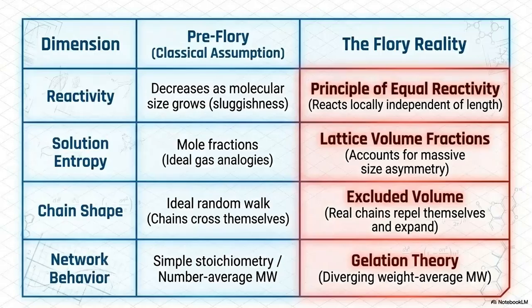For solution entropy, he replaced inadequate ideal gas analogies with lattice volume fractions, which account for massive size asymmetries. Regarding chain shape, he updated the ideal random walk assumption to incorporate excluded volume, recognizing that real chains repel themselves and expand. Finally, for network behavior, Flory replaced simple stoichiometry with his gelation theory, identifying a diverging weight-average molecular weight. Flory fundamentally rewrote the rules of polymer science.